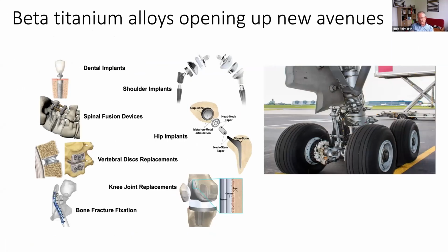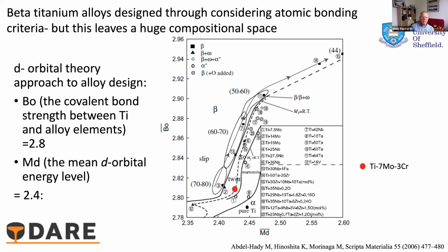Last but not least, I'm going to go through this relatively quickly, but I just wanted to mention titanium alloys as well. There is a lot of interest in the beta titanium alloys for applications such as undercarriages, where really the strength matters, but they also have much lower stiffness, and so there's much interest in biomedical applications. Now, much of these alloys have been developed on the basis of what's called bond order, d orbital energy level graphs. So we plot these 2 variables, and that's just a plot there of all the different alloy additions that have been made. And you can get yourself another paper by putting yet another alloy composition within there.